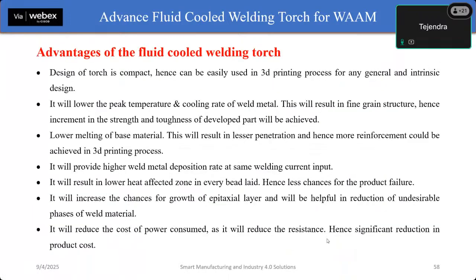So the torch with the lesser amount of temperature has been selected as our fluid cooled welding torch. The advantage of this torch is the design is compact and can be used in 3D printing process very easily, and can be used for any general or intricate designs. As the preheating of wire is already there, it will reduce the peak temperature and the cooling rate of weld material, which will result in a finer grain structure. Hence, an increment in the strength as well as the toughness of the developed part can be achieved easily.